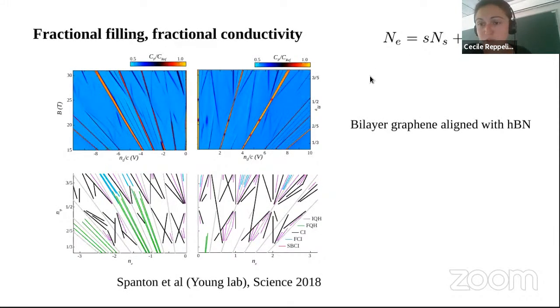What's quite cool is that, again, thanks to this enlarged unit cell allowed by Moiré superlattices, you can explore all different types of combinations of S and T being non-zero and also being fractional or integer. Here I am showing you some data that comes from Andrea Young's lab. Here it is a Bernal stacked bilayer graphene aligned with the substrate of hexagonal boron nitride. The origin of the Moiré superlattice is again, like the previous data I showed, due to the lattice constant mismatch between graphene and hBN.